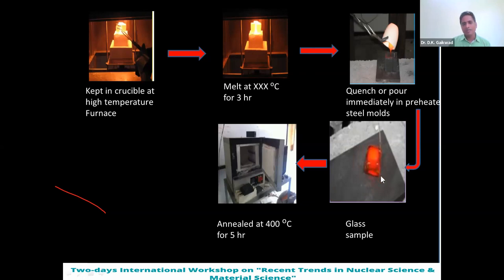Then this glass is transferred to the furnace for annealing at different temperatures, depending on the composition, for 5 hours to reduce any stresses in the glass. This is how we get the glass.